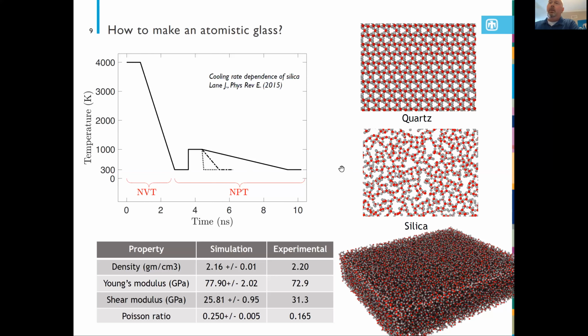People in the past have done quite a bit of work of quantifying the structure relative to experiment, and you can do so almost nearly directly using neutron diffraction or using X-ray diffraction data. With that data, you can actually almost directly compare it to molecular dynamics. I note that if I push, pull, stretch, etc., this silica sample, I can back out, say, the elastic tensor. So I know that its density is relatively close to experimental at this point, and its elastic properties are somewhat consistent with what I would find experimentally. I note that the shear modulus is slightly lower than experiment, and the Poisson ratio is slightly higher than experiment. That's not too uncommon, and I note that using this atomic potential, it does significantly better than many of the other silica-based interatomic potentials. So I think we're doing quite well in terms of comparison to experiment at this point.